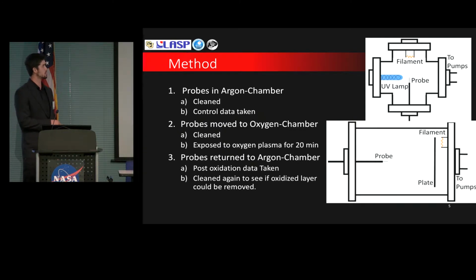First, each one of these probes, there was a wire probe, as I showed in one of the very first slides, of each metal: titanium nitride, gold, all of them. Each one of these probes was put into an argon chamber, a vacuum chamber with argon gas. Plasma was created. The probes were cleaned via in situ methods, and then a data sweep was taken for a control measurement. Once control measurements were done, the probes were removed from that chamber and moved into the oxygen chamber, where an oxygen plasma was introduced with the addition of a UV lamp to photodissociate diatomic oxygen into atomic oxygen.